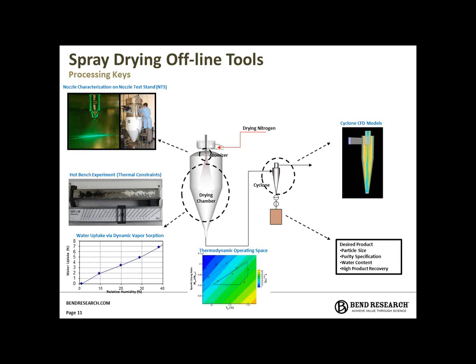Similarly, in terms of the inputs into the drying process, we can use a thermal temperature gradient hot bench experiment and define key thermal limitations that can be inputted into the inlet and outlet temperature constraints of the dryer. As Jeff mentioned, for water content, we can link water uptake versus relative humidity with dynamic vapor sorption experiments for a given formulation, and link that to the thermodynamic operating space, where we can define what the outlet RH of the spray dryer is and control water content in that manner. Likewise, we can utilize CFD models to optimize the drying chamber geometry as well as the cyclone geometry to hopefully meet our desired product profile with minimal compound requirements and development times.